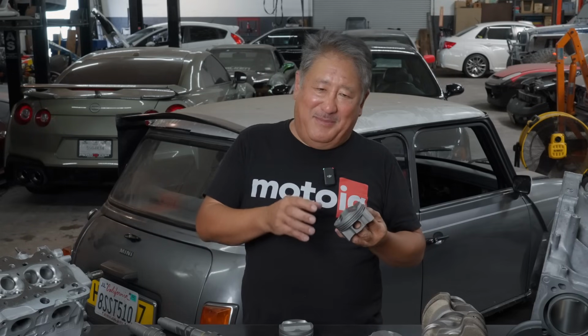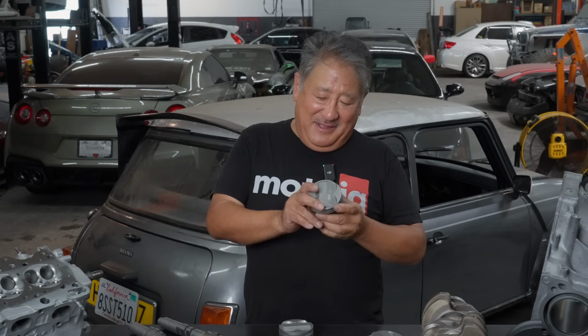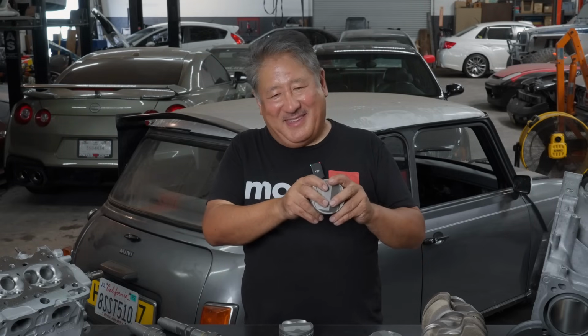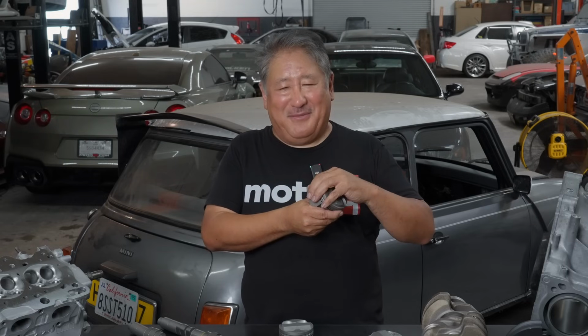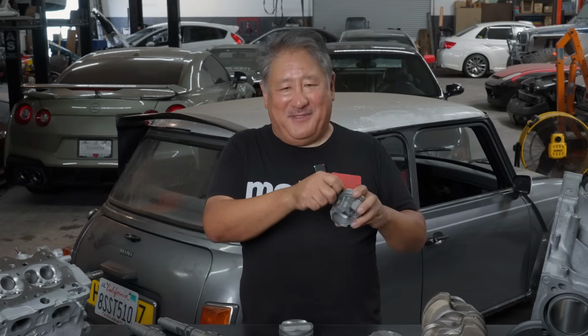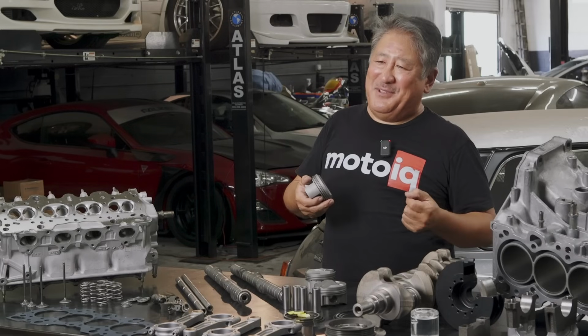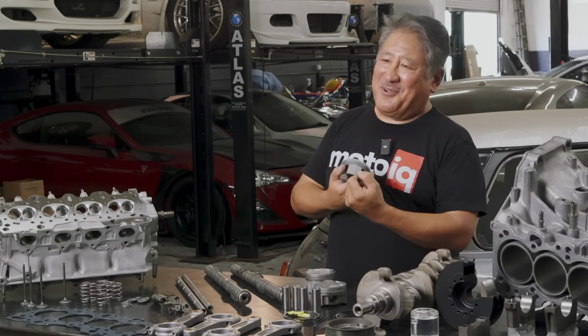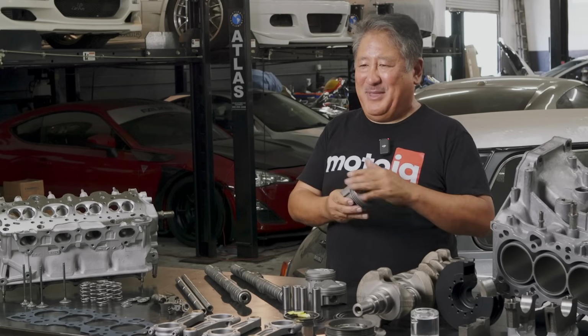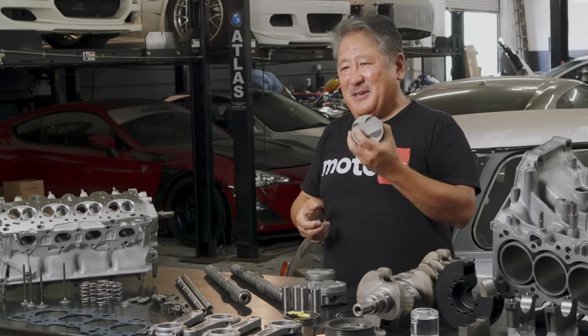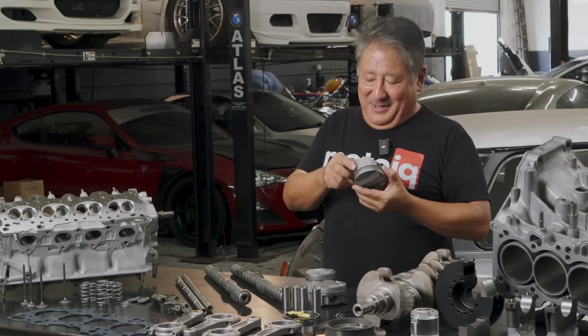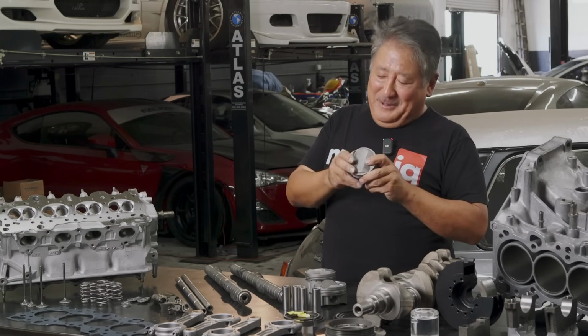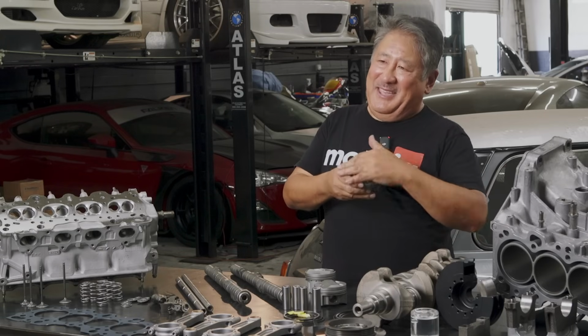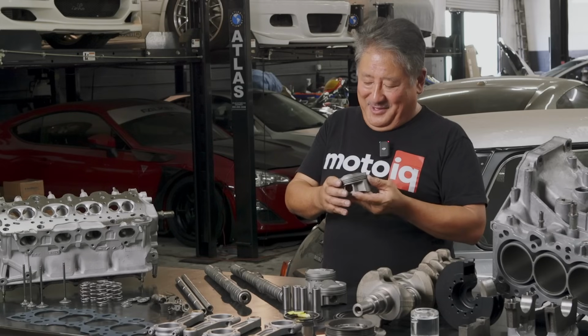The forging itself is a really good part. Now JE invests in making a lot of forging blanks for a lot of their applications, so you get a near net shape blank. This means that you have optimal compaction of the metal during forging and good grain flow. So the grain goes around the piston pins, so it acts like grain of the wood. It's really hard to snap wood when you bend it against the grain, but if you bend wood with the grain, it's a lot stronger. Same thing with getting the good grain orientation of your piston with a proper forging blank. So you get a near net forging, doesn't require that much post-forging machining, and you get optimal grain flow and optimal strength.